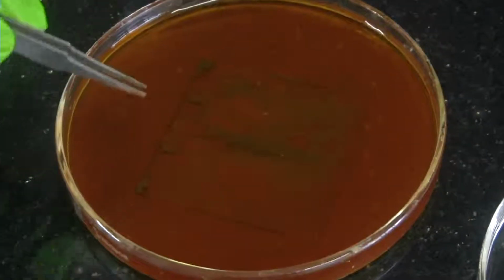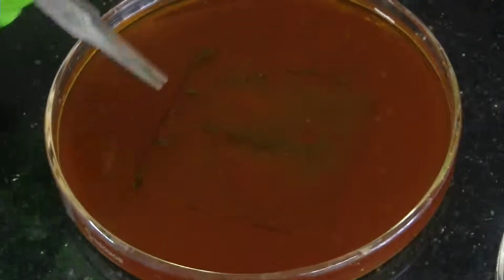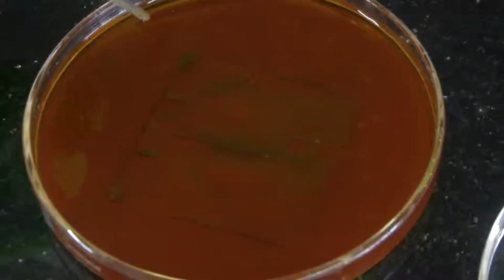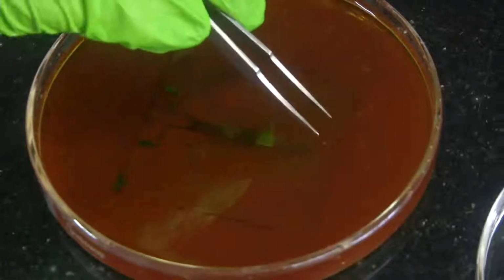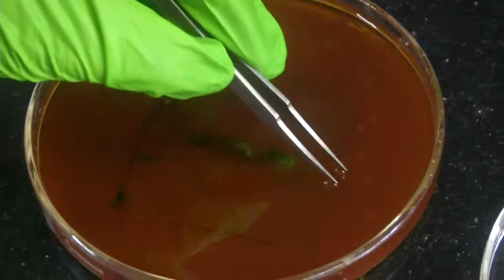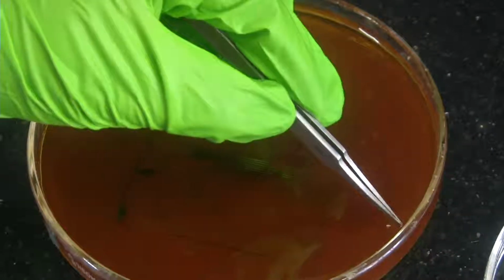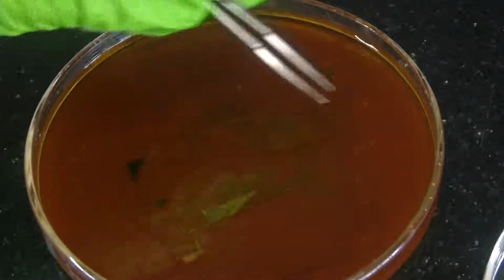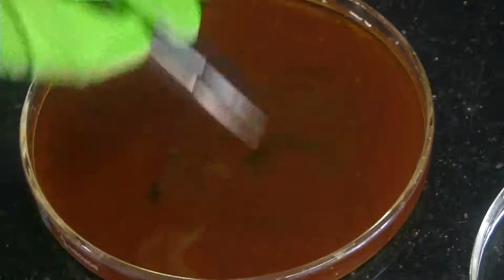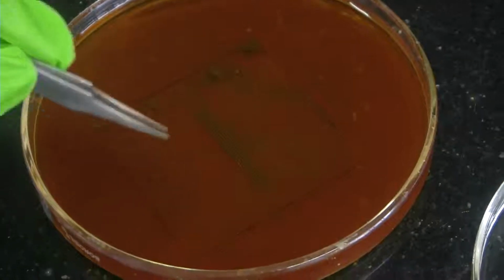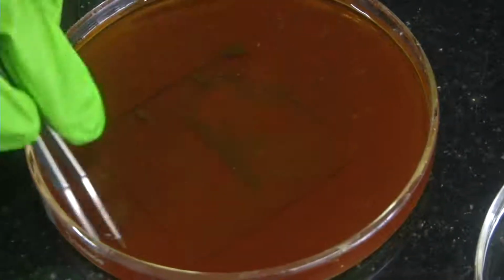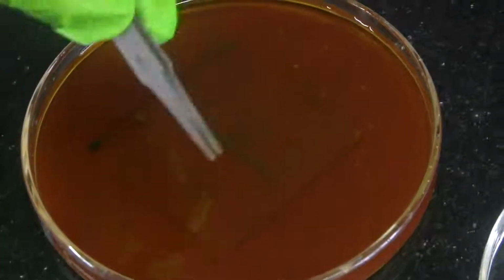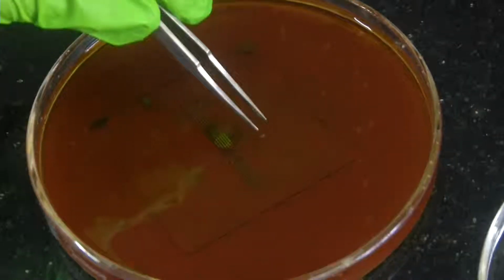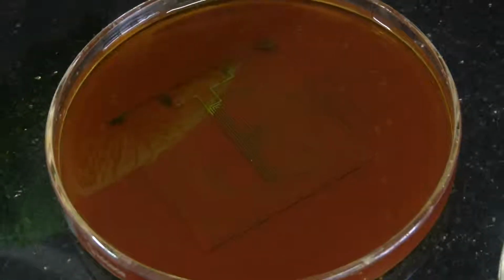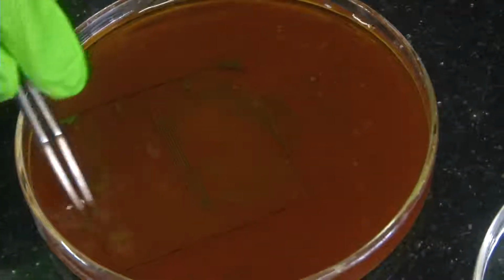Sometimes what happens is, because of process variations, especially sputter deposited metal is very difficult to etch. Usually e-beam evaporation is preferred for etching. Because this is sputter deposited gold, there is some non-uniformity in the metal deposited on the slide. That is why in some part the metal is removed and some part it is still there. So let's just wait it out and see if it goes. If it doesn't go, that is also a problem with the metal that is deposited because of the process. But here reasonably it is going.